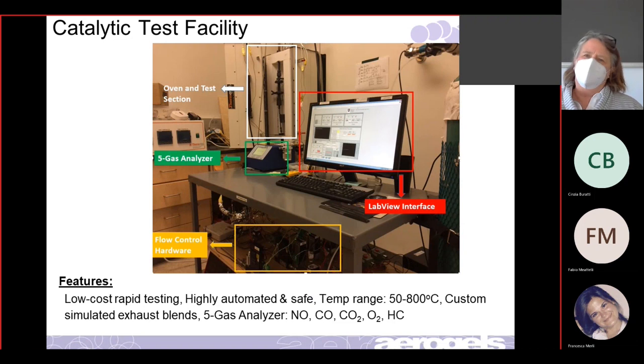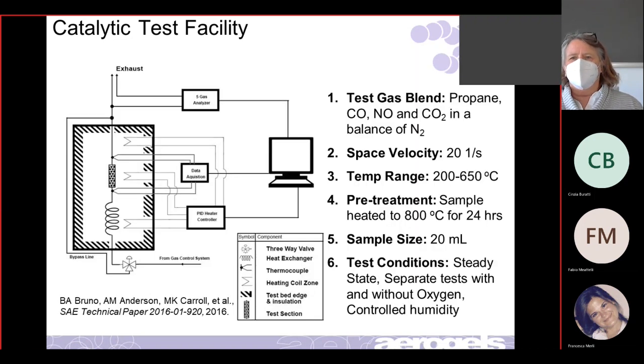So some of the things we care about. Here's a schematic of the oven. Here's the flow coming in. There's a heat exchanger there to make sure the gases get hot. Here's the test section where the sample goes. We measure the temperature here and here, and actually we measure inside the sample too. This is an oven, so all of this is heating that up. And so we flow through.